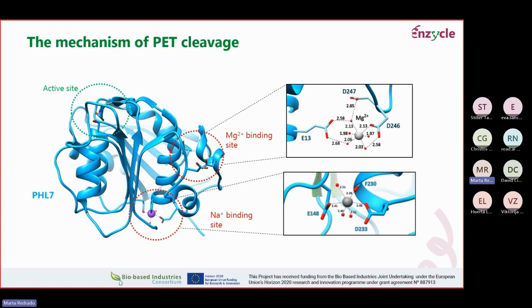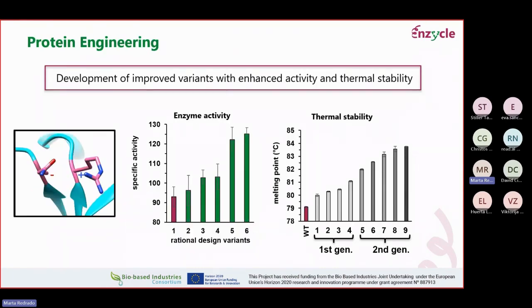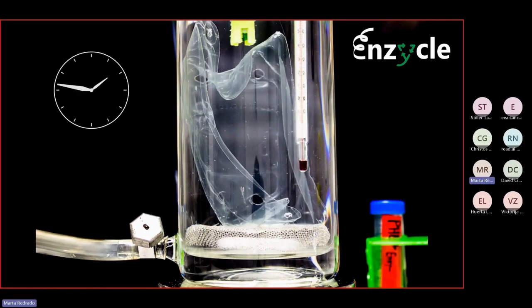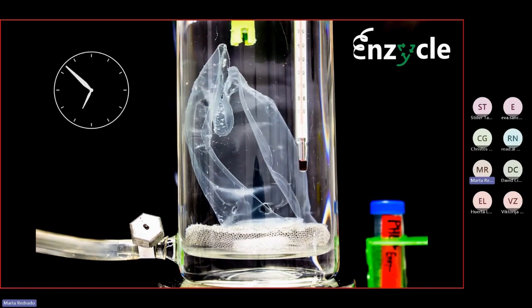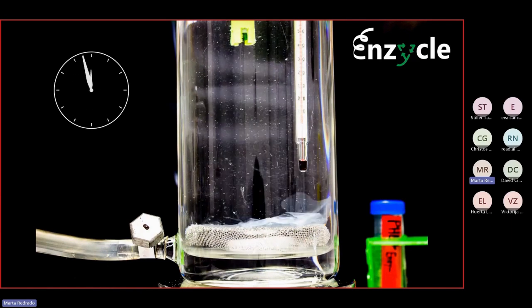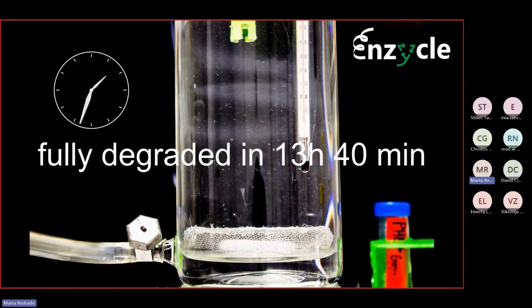Once we identified the most relevant residues, we were able to modify them to improve the characteristics of this enzyme, which we did. For instance, we were able to obtain new variants of this PHL7 enzyme, which showed better activity rates and also a higher thermal stability, which are features highly desirable when we are using these enzymes in PET degradation processes. And with these efficient enzymes, we managed to fully degrade PET trays in a relatively short time. So these are very good results.